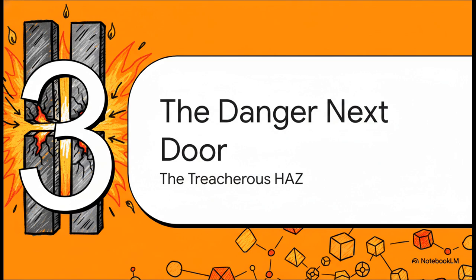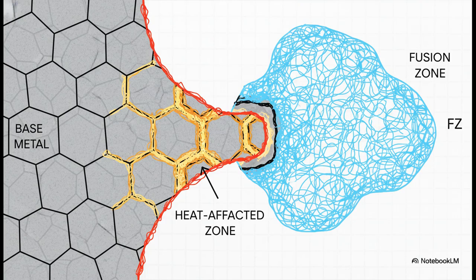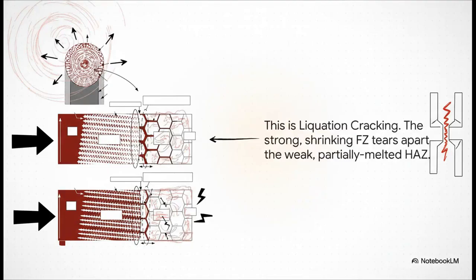So the fusion zone is tricky for sure, but the real danger, it's often lurking right next door. Let's shift our focus to the HAZ, where the metal gets cooked, but not completely melted. This is the spot, the most dangerous area. It's not the liquid pool, and it's not the untouched base metal. It's this weird transitional boundary inside the HAZ. Here, the heat is just hot enough to melt the weakest parts of the metal structure, specifically along the edges between the solid grains. And that weakness leads to this nasty business, liquation cracking.